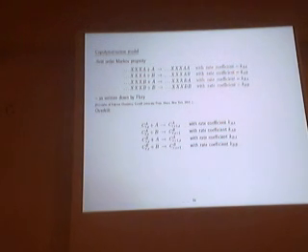What we don't understand is how this colloidal particle can continue to grow, because they are probably strongly hydrated, and therefore they have different properties compared to the solid, because if you take the solid out and put it inside, it doesn't work. Only these clusters which are formed, and once they are formed, they induce very high stereospecificity. So your model is actually the first part of the experiment, and because we use amino acid as initiators, where the percentage of this initiator is very, very low, and the reaction competes with hydrolysis, you cannot do that. So we probably need to go back to here and add in other effects, but we should talk about that later.